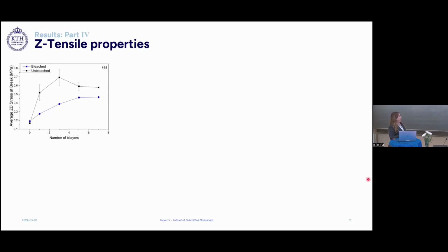The Z strength of the paper is mainly affected by the strength of the fiber joints, as opposed to the tensile strength of the paper, which is more affected by the strength of the shear fiber wall. Therefore, by evaluating the Z tensile properties of the paper, we can evaluate the effects of the treatment on the fiber-fiber joints. By doing Z tensile tests on the LBL treated papers, we also see an increase in the strength of the paper, both for the bleached and unbleached materials.